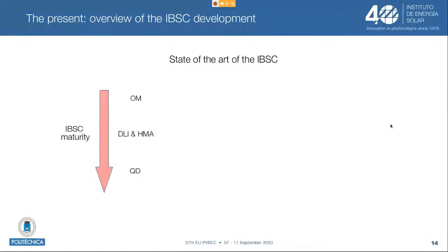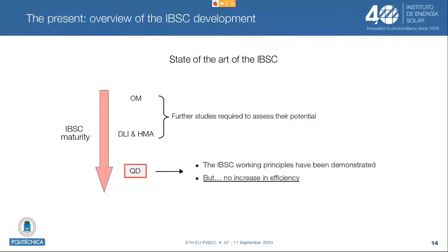I will tell you a little bit about the state of the art in these approaches. As concerns intermediate band solar cell maturity, organic molecules are the least advanced because they were proposed very recently, and there are only a few devices fabricated so far. Deep level impurities and highly mismatched alloys have been much more studied. In particular, they have given very good results in terms of extra photocurrent, but there is an important reduction in voltage due to non-radiative recombination. So these technologies still need further study to fully assess their potential. And finally, quantum dots have been the most explored and successful technology so far. They have demonstrated the operating principles of intermediate band solar cells, but still no practical device with an increased efficiency has been demonstrated.